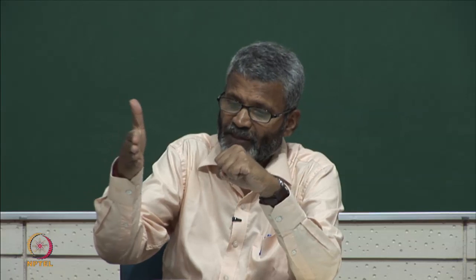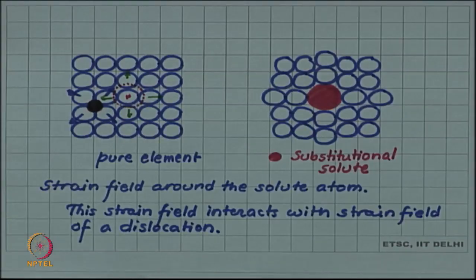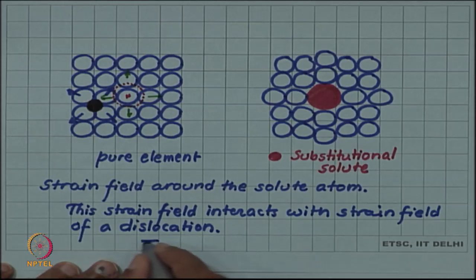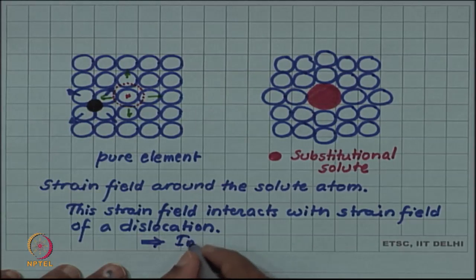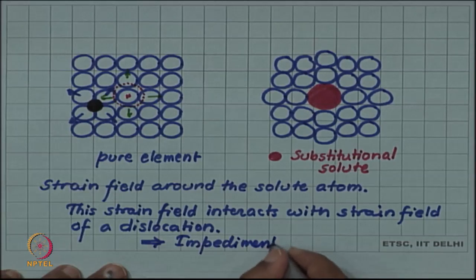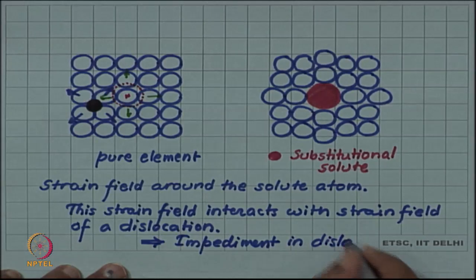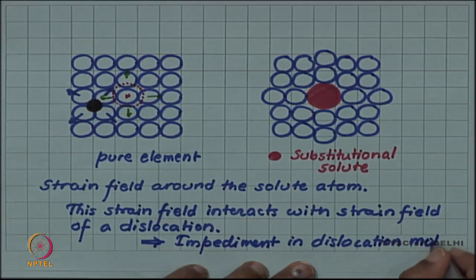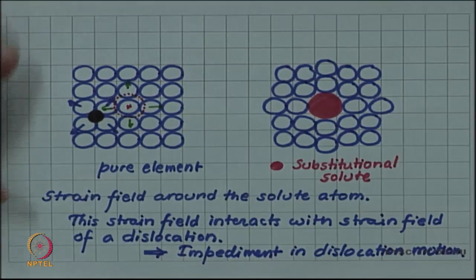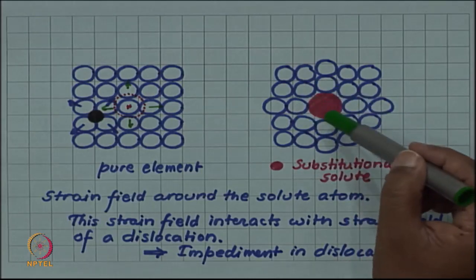So, if the dislocation line is being repelled by the solute atom, the motion will be impeded. But suppose the tensile of solute atom overlaps with compressive of the dislocation line, then there will be an attraction and the edge dislocation will like to come close to the solute atom. But in this case also, if it wants to continue to move to create further plastic deformation, it will not like to move away because there is an attraction with the solute atom. So, in either case, the strain field interaction with the dislocation strain field causes impediment in the dislocation motion. Also note that an important factor here will be the size difference.